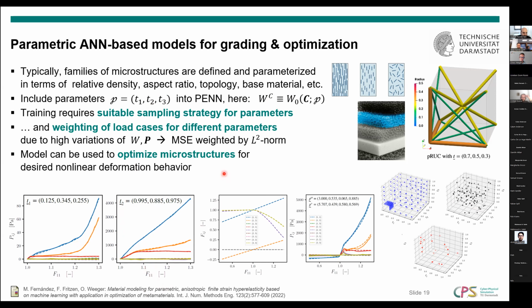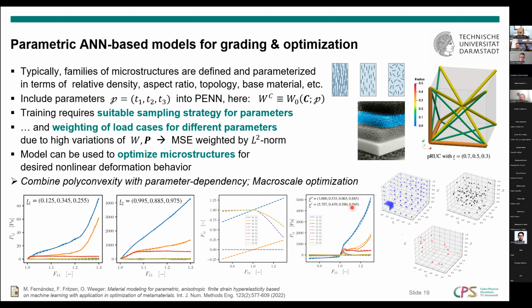Now, if we have such a parameter-dependent model, we can use it for optimization. So basically, we can say we want to have a desired response behavior, a desired stress-strain curve. Now, please find us the corresponding parameters. So basically, we use the nonlinear optimization for these 3 design parameters on top of the constitutive model in order to get the parameters that would give us a certain behavior. This worked quite well, but as I said, we did not combine this here with the polyconvex model. And this is not 100% straightforward, because you have this convex dependency on the deformation gradient, which you would need in your model, but the dependency on the parameters might not necessarily be convex. So basically, we will have to combine different network architectures that can take into account convexity with respect to some inputs, but not all of the inputs.